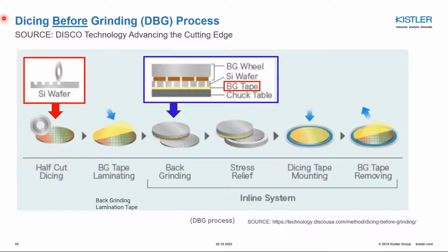In the second step, shown as yellow film, the back grinding lamination tape is placed over the wafer. This protects the wafer's printed circuit side. In the third step, shown in the blue box, the wafer is flipped and back grinding occurs from above. It is in this step the wafer is thinned and each die separates from one another, then only being held in position by the back grinding lamination tape.